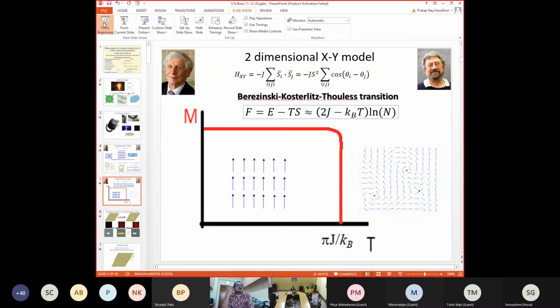David Thouless and Kosterlitz got startled. Because when you think about it, this is not a first order phase transition. Look at this free energy. The free energy does not have any discontinuity. It is going smoothly across the transition, nor do the derivatives of the free energy have any discontinuity. So it's not a first order transition, it's not even a second order transition. It's a transition where the free energy is just smoothly going across the transition. And that is when they realized that they had discovered a new kind of phase transition, which is actually an entropic transition, which we now know as the Kosterlitz-Thouless transition. And this is what got them the Nobel Prize many years later.